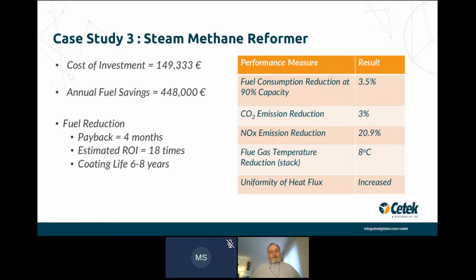And on the left-hand side, you can see the commercial aspects of this application. The cost was about 150,000 euros with an annual fuel saving of almost 450,000 euros. So the payback on fuel reduction was around 4 months, and the estimated return on investment was about 18 times over the coating life of 6 to 8 years estimated. So they were very happy with those results, as anybody should.